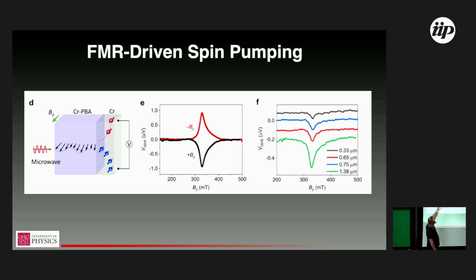You can do it with a metallic magnet, and that has given rise to endless PRLs analyzing artifacts and trying to disentangle what's happening. Yttrium iron garnet, with apologies to Georg, is the villain of this story, because it is the canonical system that does this extremely well. It's highly insulating and has very sharp magnon resonances, so it gets rid of most but not all potential artifacts. This Prussian blue analog is taking the role of YIG in a more conventional, all-inorganic structure.